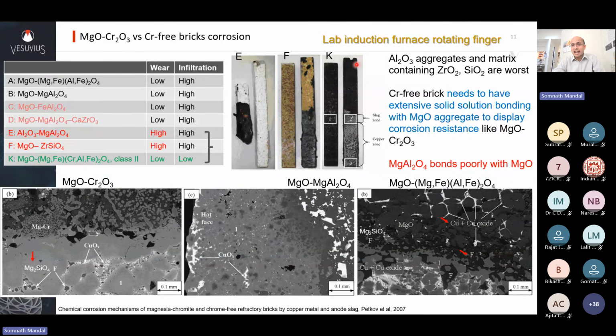They did a lab induction furnace rotating finger test. You have bars of refractories dipped in copper, sorry, and rotating in copper slag. And you have the metal line and then you have the slag line. And obviously we'll have more corrosion in the slag line. They studied a variety of refractories, from magnesia-chrome, the traditional one, versus magnesia zircon, and then alumina spinel.